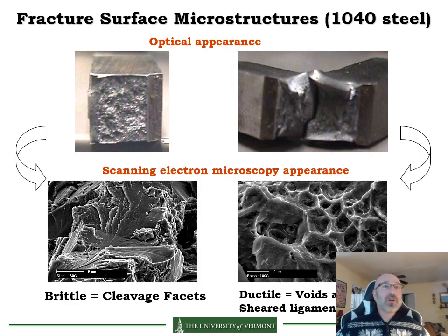The other thing to consider here is the fracture surface of the microstructure. So we're going to take a look at this under a scanning electron microscope. Even just a close-up, not even high resolution, a medium resolution photo here, we can see the difference between a brittle break and a ductile material. You have a brittle material over here on the left, and a ductile material over here on the right. You can see a little bit more necking going on with the ductile material, and you can see how it stretches before it breaks, whereas the brittle one just snaps almost clean through. And when we zoom in, you can see the cleavage facets in this brittle material on the left, whereas you're seeing more of these voids over here on the ductile material on the right when looking at it through a scanning electron microscope.